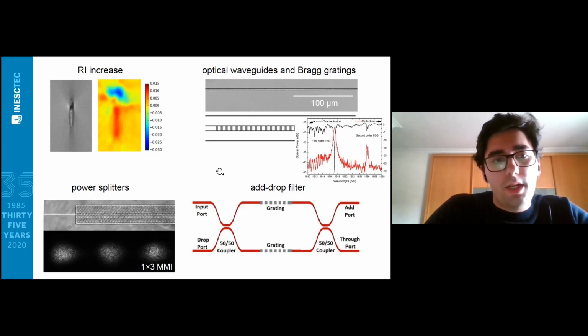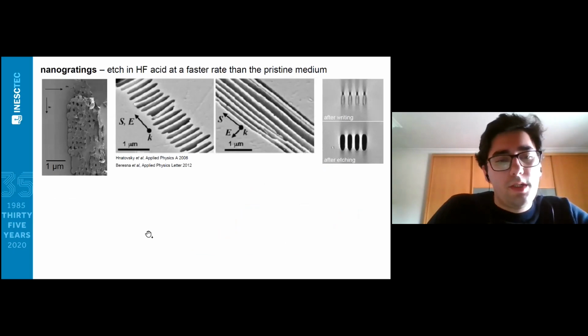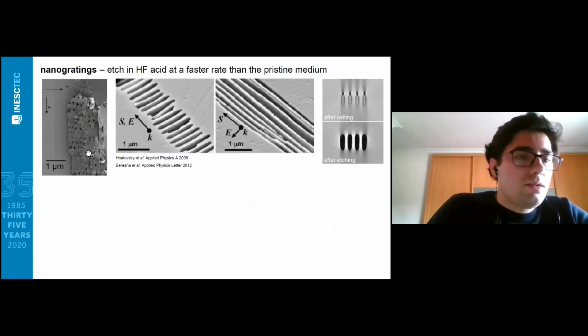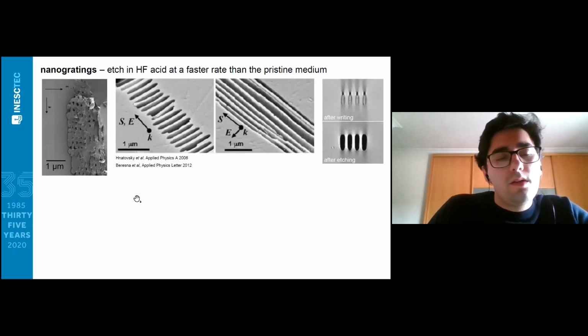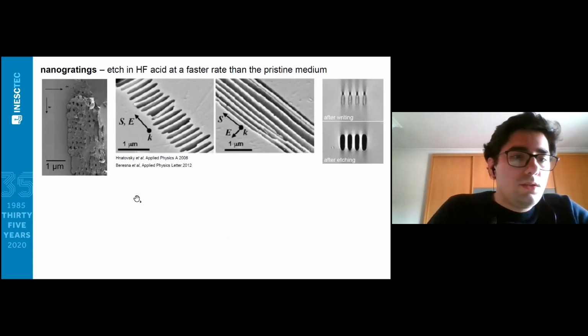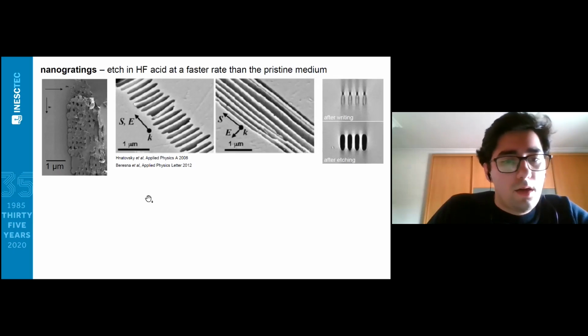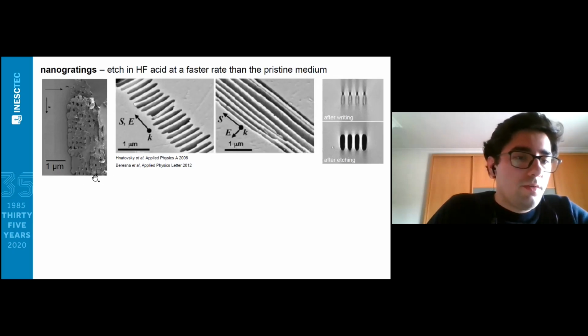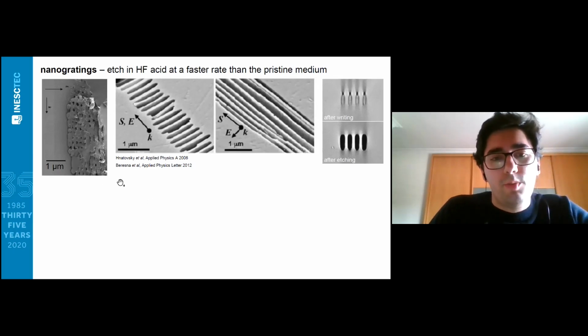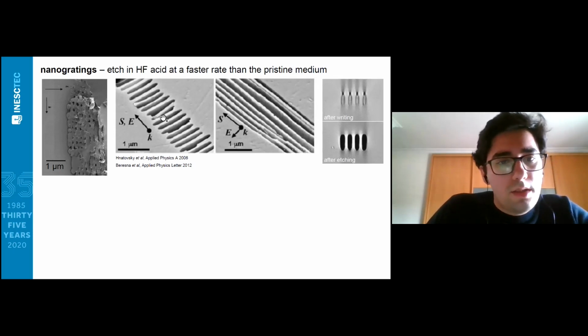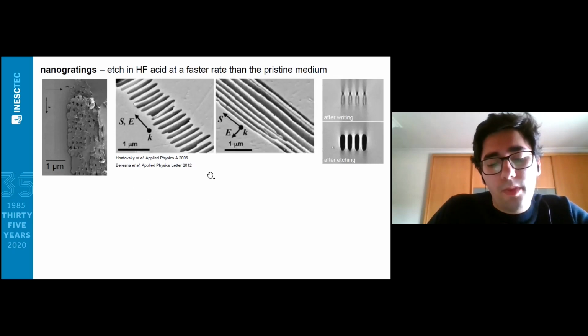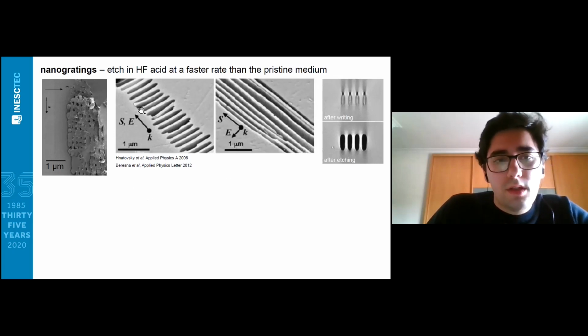The other possible modification you can have in fused silica is related to the formation of nanogratings. As you can see here, you have these periodic nano layers, which are darker in this picture. These are self-organized layers of modified silica, in this case porous silica, and the existence of this structure is what allows us to fabricate microfluidic channels. As you see here, when we immerse the substrate in HF acid or in potassium hydroxide at high temperatures, these layers will be etched at a faster rate than the pristine medium.